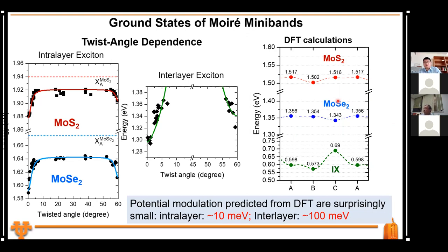We measured this moiré potential amplitude. This is the band gap variation, about 150 meV. And then we also show the DFT gives you an amplitude of about 100 meV. And this is a very similar system, right? The only difference is now it is MoSe2 instead of WSe2. So you see this, but the intralayer is very small. And you go to any DFT group, they will tell you this is small. But why do we see such a large variation in the intralayer exciton?